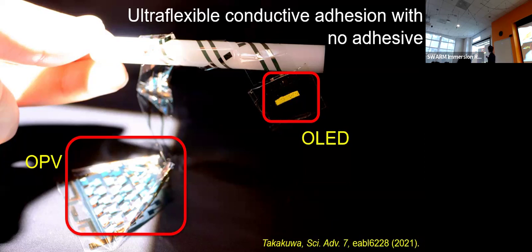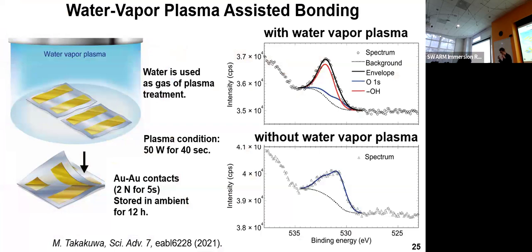These two devices are connected with these gold films without any conductive adhesion materials. And then here I show more details of the processes. The process is very simple. We prepare two gold films onto very, very thin substrates. In this case, we use polyimide as the polymer substrate. And then we apply the aqua plasma, the water vapor plasma, onto the gold surfaces to activate the two gold surfaces. And then after that, we overlap these two gold layers. And then we store this overlapped gold in ambient air conditions, at room temperature, for several hours, maybe 12 hours. Maybe a shorter storage time should be okay, but we stored for around half a day to make a perfect bonding.